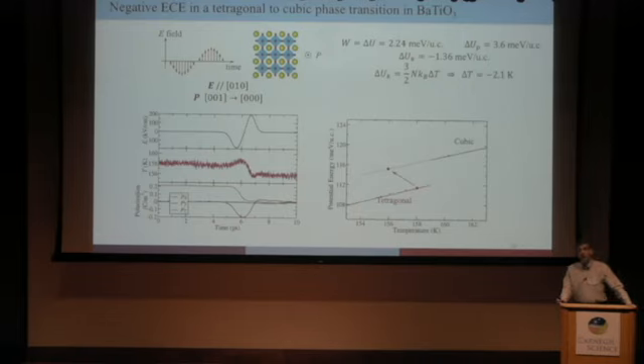This serves to scramble the electric dipoles quite effectively. They don't have time to, in an adiabatic way, rotate and follow the electric field, because by the time they do, the electric field is the other way, and it has the consequence of just convincing the individual dipoles to scramble. If we make a graph of the volume average polarization along the X, Y, and Z directions, it's tetragonal with polarization along Z, it starts to rotate into the Y direction, but pretty quickly it all scrambles, and it goes to the cubic local minimum in free energy, as opposed to finding one of the tetragonal variants. And so this leads to a change in temperature of more than 2 Kelvin.